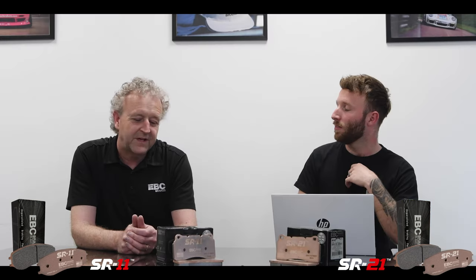So Steve, what is the difference between an organic product such as our RPX pad and these sintered pads? Well, organics are basically most pads out in the marketplace and they're bonded with a resin which holds all the other ingredients in place. A sintered pad is actually a fused metal matrix, so very much stronger and very much more temperature resistant.